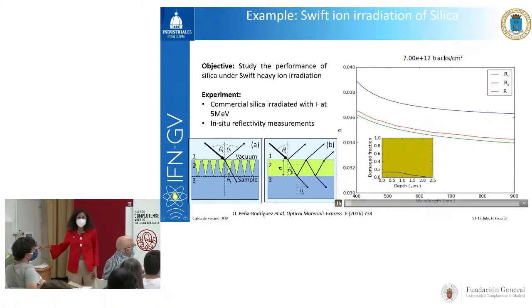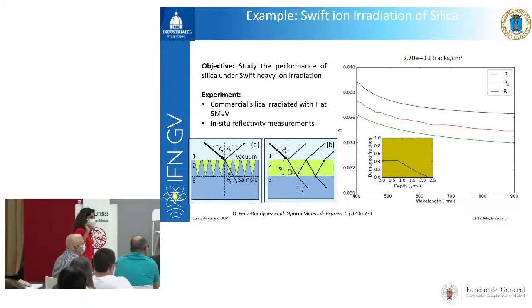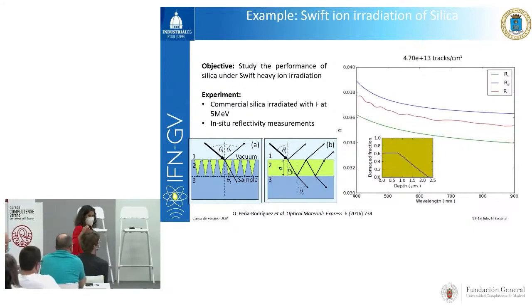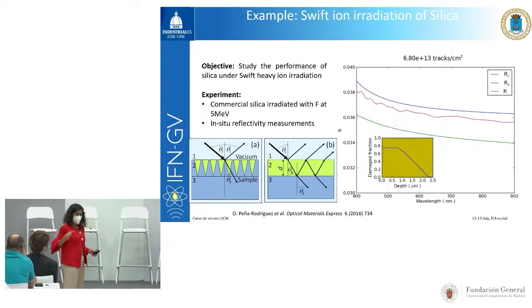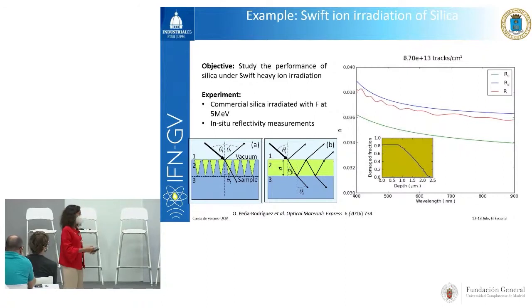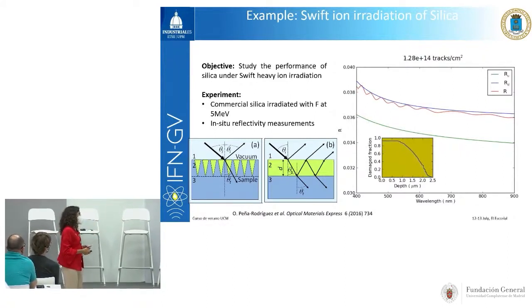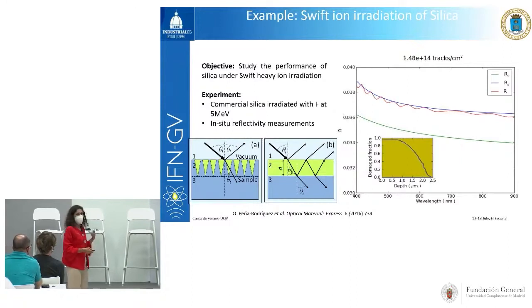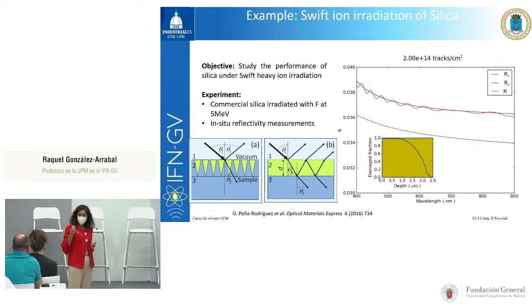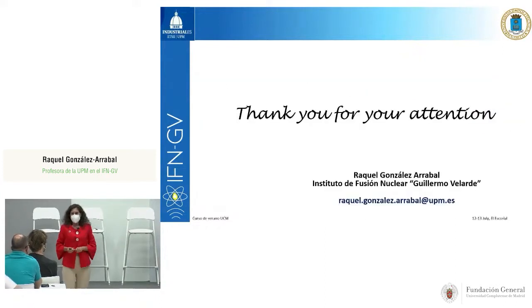And you may see this is for every particular fluence. So it is not that we measure the sample, take it out and measure again, and so on. We can characterize the optical response in situ, and out of this data, by using models, you can characterize, for example, the ion track radius and so on. So you can really obtain very valuable information.